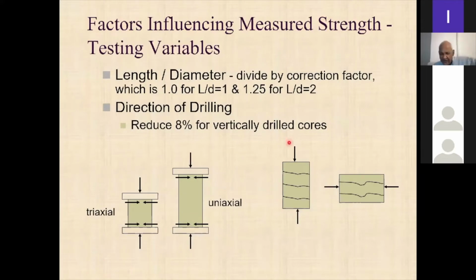Then this is just to indicate that, now when you test this in a compression testing machine, if you test length upon diameter ratio equals 1, then you will get a higher strength because you have this triaxial effect. Like you are trying to push this concrete together, but the concrete will try to expand because of the Poisson effect. It is prevented from expanding by the friction with the platen here. So there is a lateral force that is set up like this, right? So because of that, this is concrete tested in a triaxial condition. Now, if you test length upon diameter equals 2, you get the same effect. But by the time you get to the center of this specimen, that triaxial effect would have disappeared. And therefore, we call this typically uniaxial strength, right?